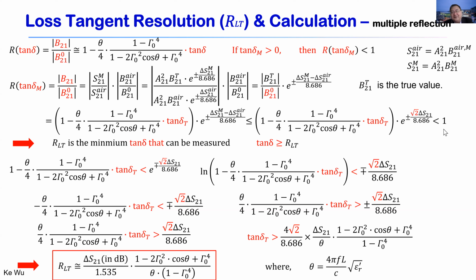But this ratio should be smaller than 1. Why? You have, for example, the transmission from interface 1 to 2 for the given material block versus the 1 to 2 transmission without loss. Definitely without loss gives you better results. So in this case, this ratio should be smaller than 1. That's very natural. So this ratio being smaller than 1 is actually a physical condition.